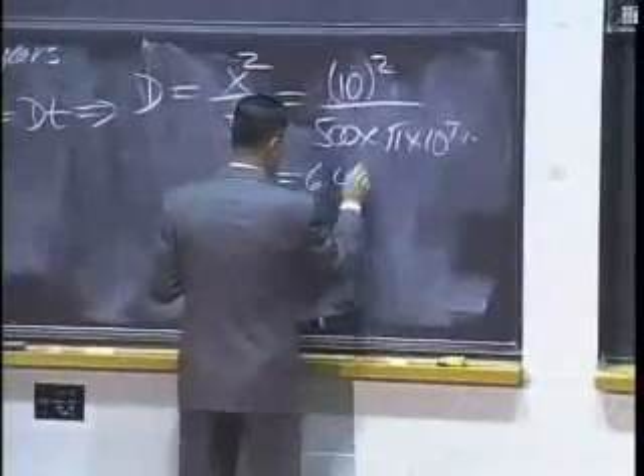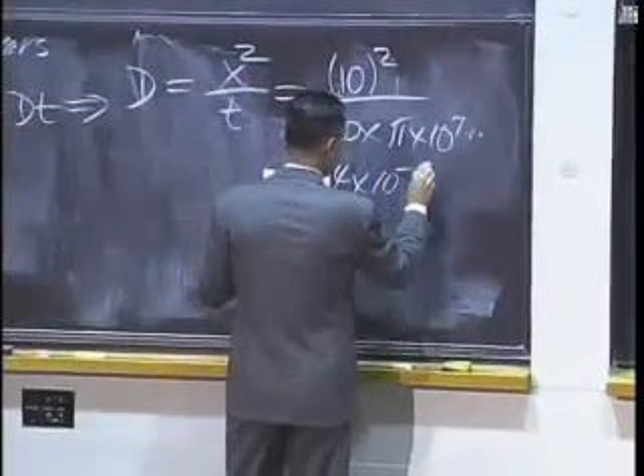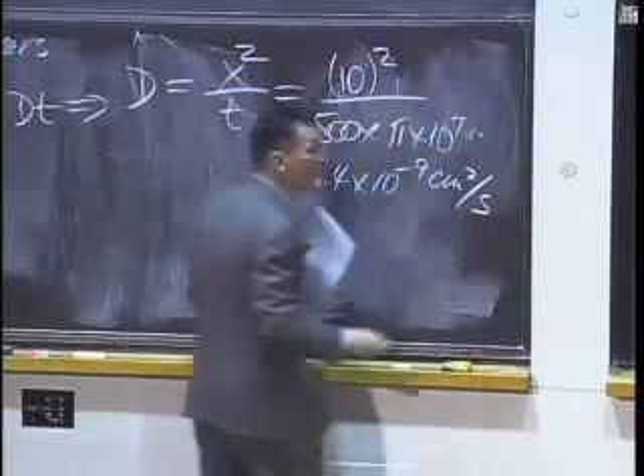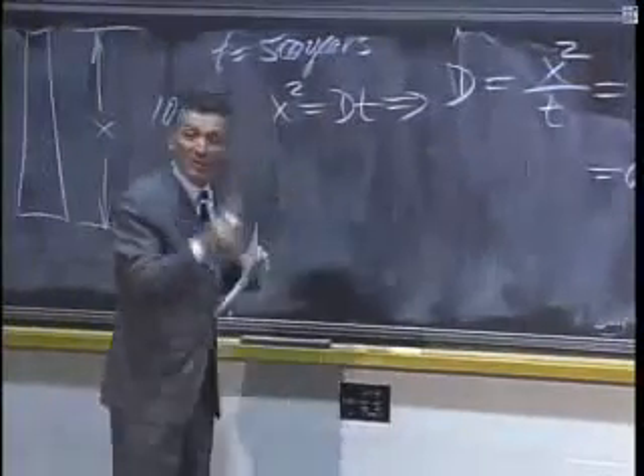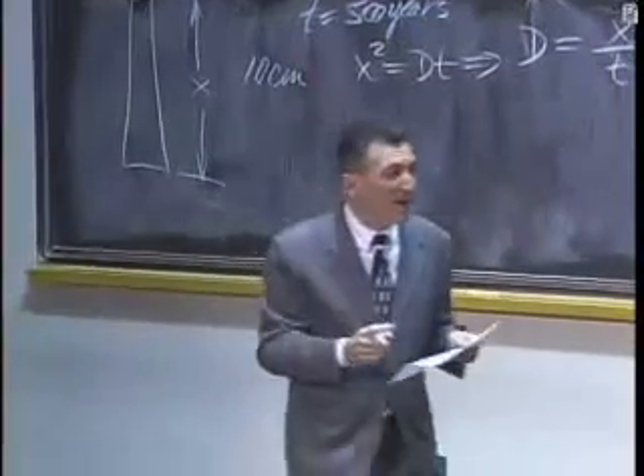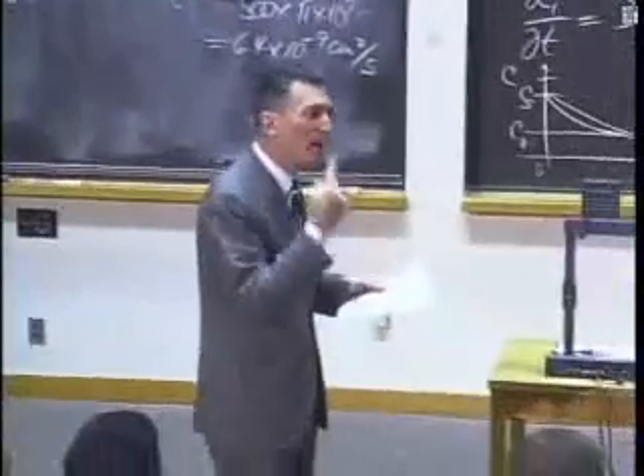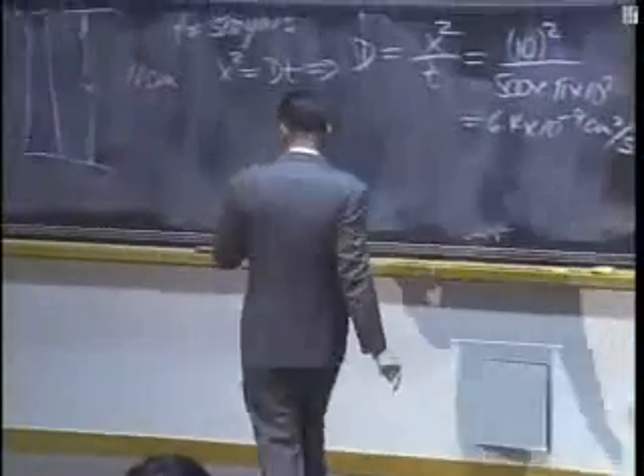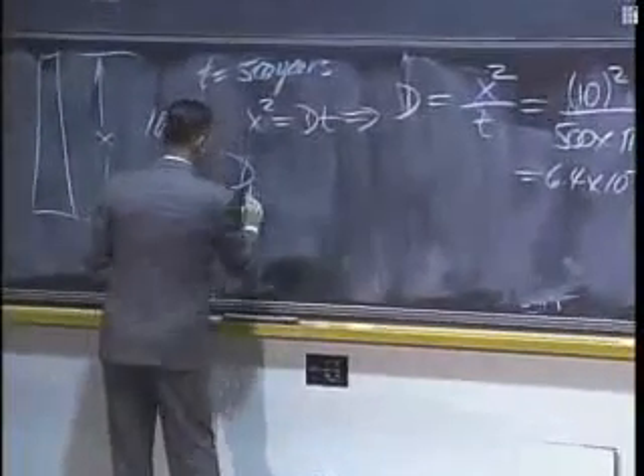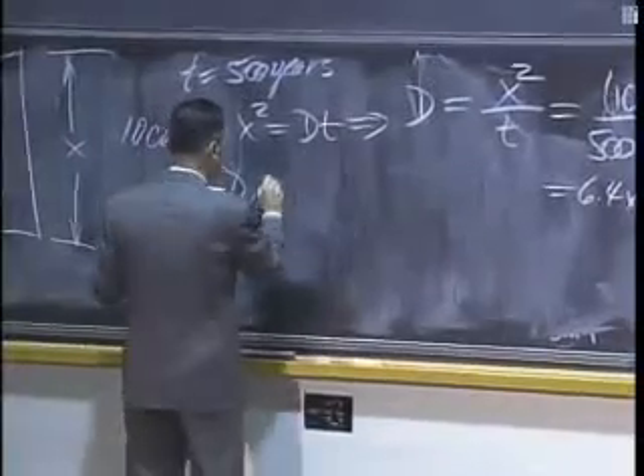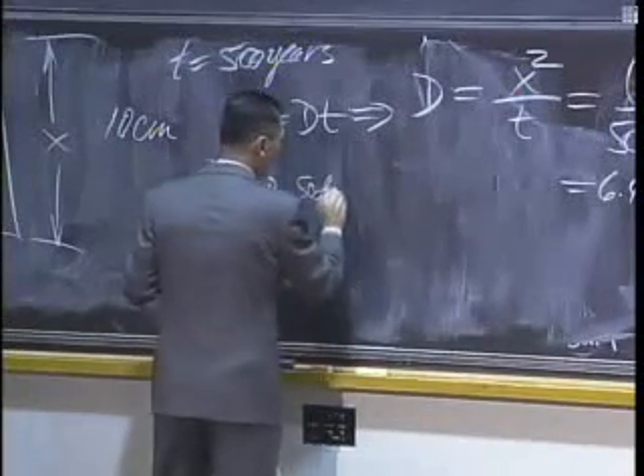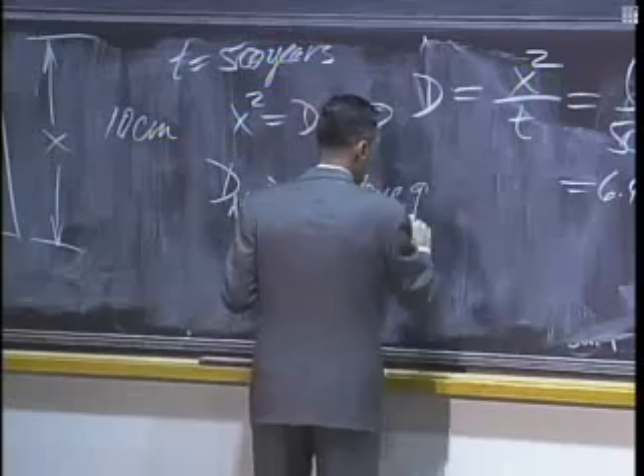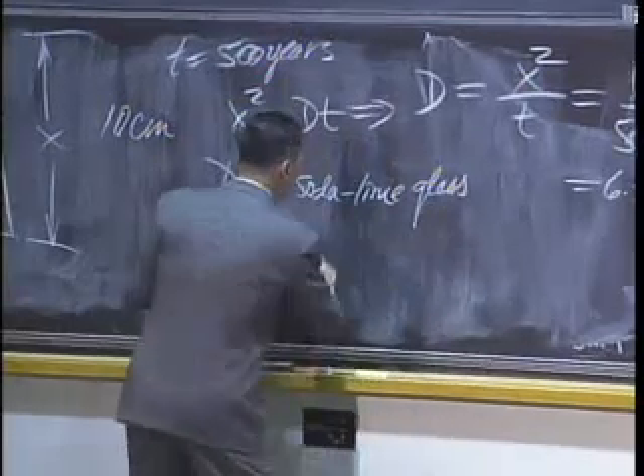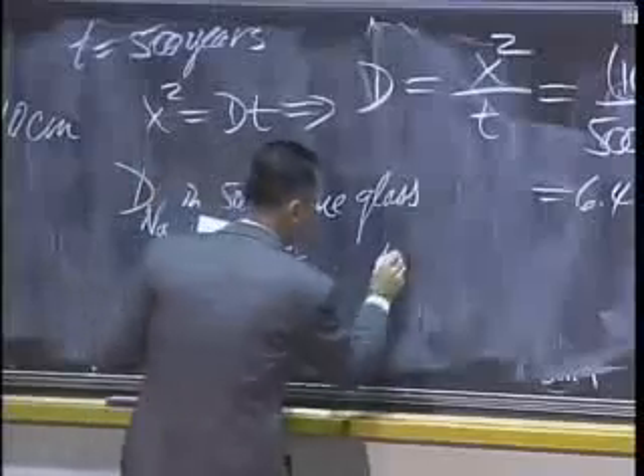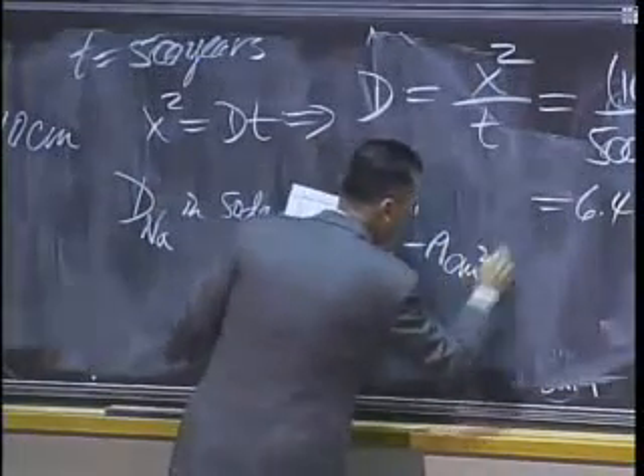All right, so 6.4 times 10 to the minus 9 centimeters squared per second. I'd need a diffusion coefficient of a silicate glass of 10 to the minus 9. I mean, that's the diffusion coefficient of a close-packed metal at its melting point. So I went and I looked up some data, and here's what I found for the diffusion coefficient of sodium in a soda-lime glass, such as the type that would be used in those windows. And using those data, at 10 degrees C, the diffusion coefficient would be 10 to the minus 19 centimeters squared per second. It's off by a mere 10 orders of magnitude.